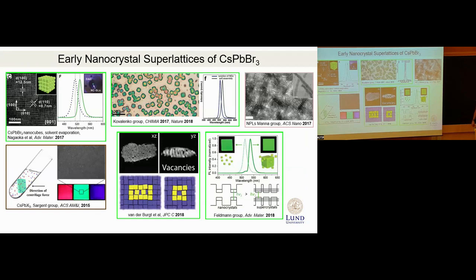Here are a few examples of the early superlattices. In 2015, for example, the Sargent group just centrifuged particles onto a solid substrate and obtained close-packed films. Then several groups were seeing these superlattices simply by slow solvent evaporation, using the typical method of depositing colloid on the substrate, letting the solvent evaporate, and observing these nice superlattices from cubes. Some groups did, I think Sarah Bals did electron tomography, identifying some defects.